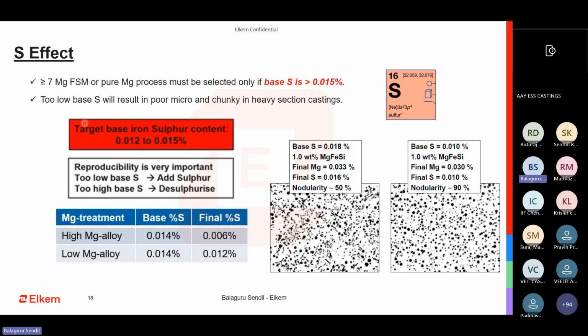There are two options of doing it. Either I can have a high Mg alloy and then I will bring down the sulfur, or I go for a low Mg alloy with higher additions. So both are not preferred. It is better to have the sulfur in control so that from a yield point of view, you have a very stable process. So you have to select your raw materials. You have to select your recarburizers in such a way that your base sulfur doesn't cross this particular limit.